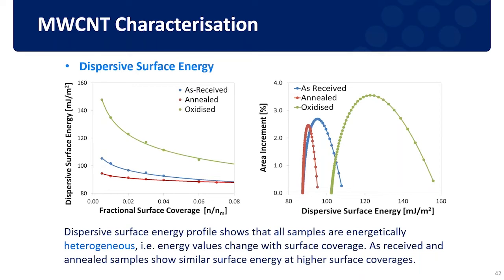And all the samples show to be energetically heterogeneous with respect to the dispersive surface energy. So the surface energy is changing dramatically as a function of the coverage. And the oxidized sample is found to be the most heterogeneous sample, with the addition of the functional groups on the surface, which makes the surface more rough or more heterogeneous. And for the annealed sample, we remove the functional groups and the sample becomes more uniform.